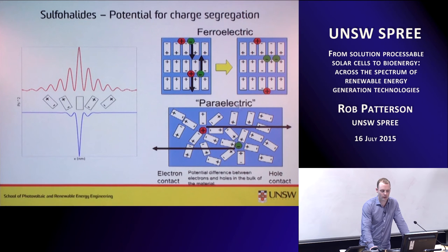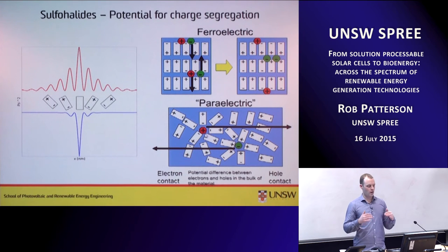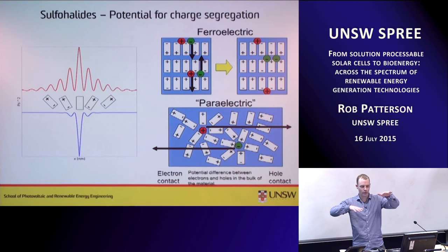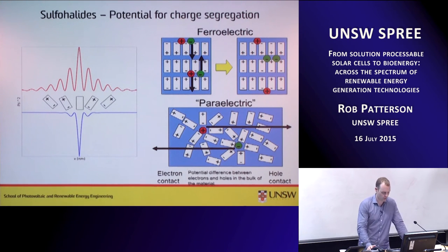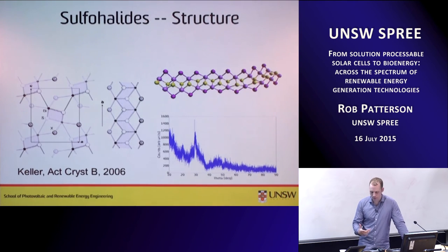And what I'm calling down here, just loosely termed a paraelectric, if you had another type of material where the polarizable domains were very free to rotate, then you could again have a screening type effect where these positively charged carriers are sitting on some pedestal, basically, and the negatively charged carriers are sitting in some valley, and they are separated by some potential difference, which is dynamic in the material. So it moves. As these charge carriers are moving, the potential difference also moves and helps to screen their interaction. So sulfohalides have the potential to make these little domain structures, and there's then the potential that this would increase screening in the material.